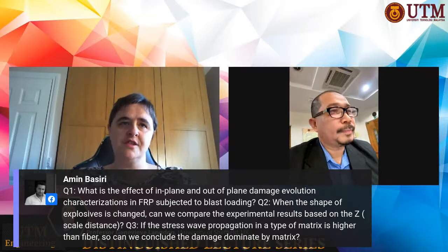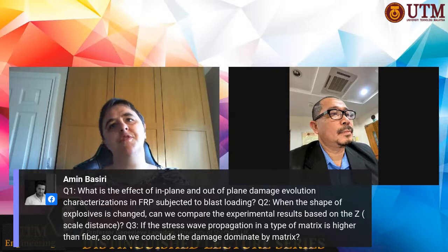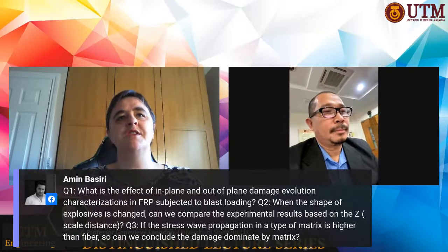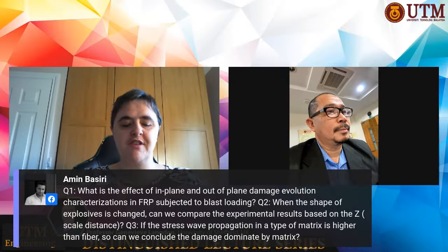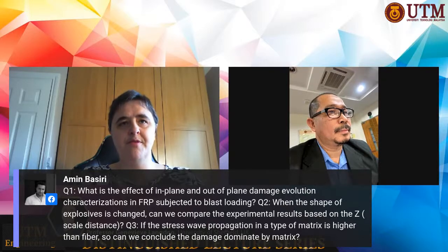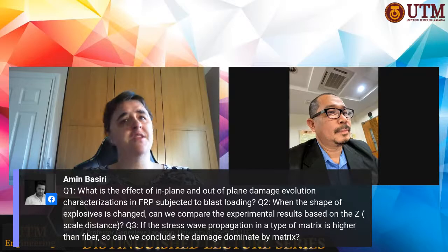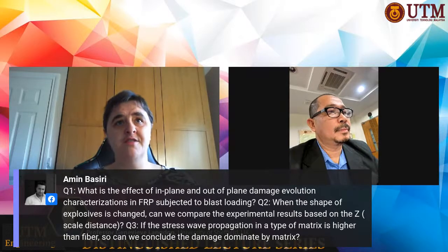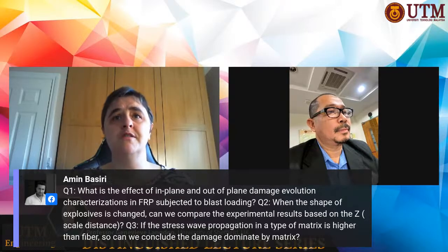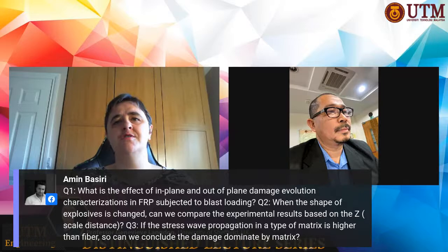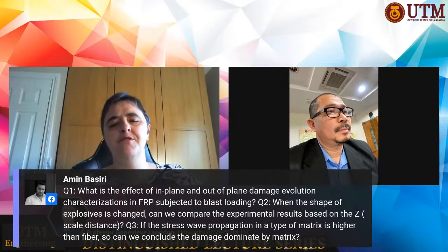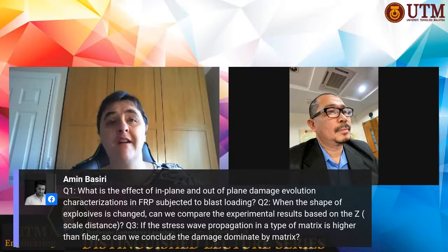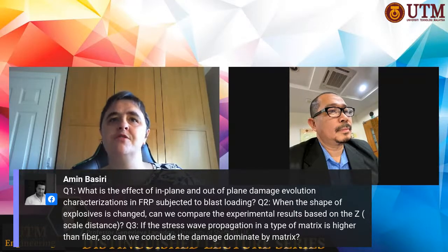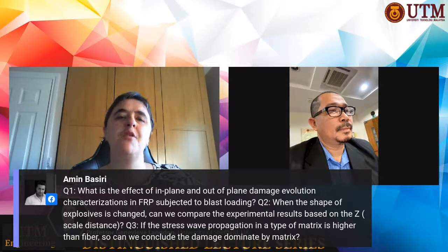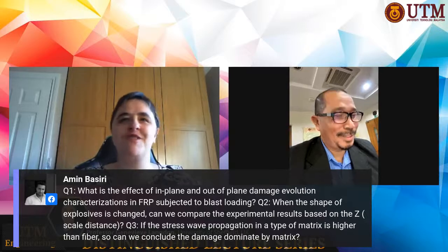So what you see is that there's a very complex interaction between all of those different types of failing modes, with delamination and debonding, fiber matrix cracking, fiber rupture. And it depends very precisely on the load type, the boundary conditions, the manufacturing type. So it's impossible to generalize without actually doing some sort of experimentation or some sort of modeling to look at it. What is really difficult, though, is to work out what the material model should look like to characterize accurately the in-plane and out-of-plane damage evolution. So it's an impossible question to answer because it's kind of everything, if you get what I mean.